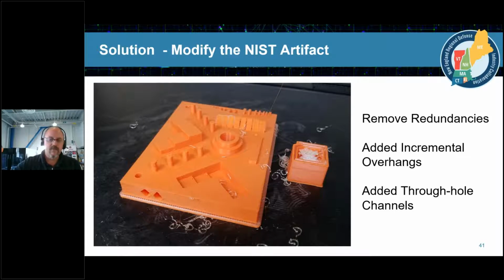So we decided next to redesign the technology, and we took the approach that most 3D printers or small manufacturers might use. We used the lowest possible costing tech. We went to a MakerBot. We revised the sample. We took out some of the duplicative data. We don't need redundancies. We just need to understand what's possible. And then we added some structures.